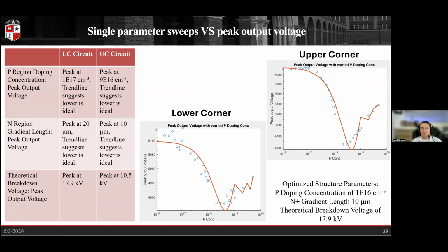So with this, we moved from the 2-parameter sweeps to single parameter sweeps. We can see the curves in these 1D graphs with these trend lines plotted here. Looking at the P region doping concentration for the lower corner circuit, we found that peak at about 1E17. And with the upper corner circuit, we found peaks at 1E16. So we can see there's some benefit to going lower, but the impact once we get lower than 1E17 begins to diminish. So it's not worth it.